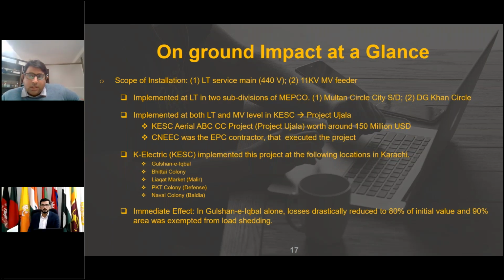The immediate effect of these covered conductors is that in Gulshan Iqbal alone, losses drastically reduced to 80% of their initial value, and 90% of the area was exempted from load shedding. This is because as per one of the directives from the Supreme Court, if the revenue from any feeder is less than 50% due to pilferage or other losses, it can be cut off from the system, as an example, to recover the rest of the system. So when the losses were drastically reduced to 80%, the 90% area got the immediate effect that they were exempted, because mostly the pilferages or technical losses were reduced to a very small amount.